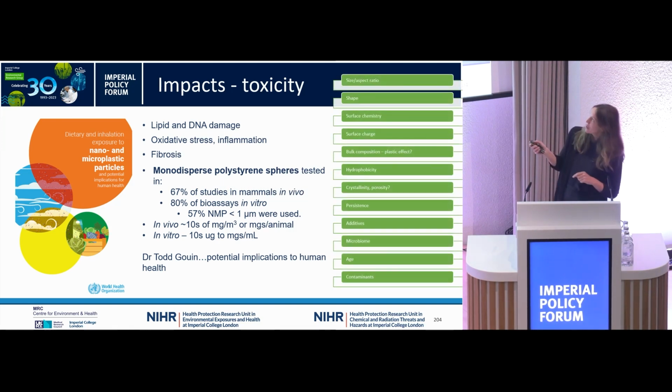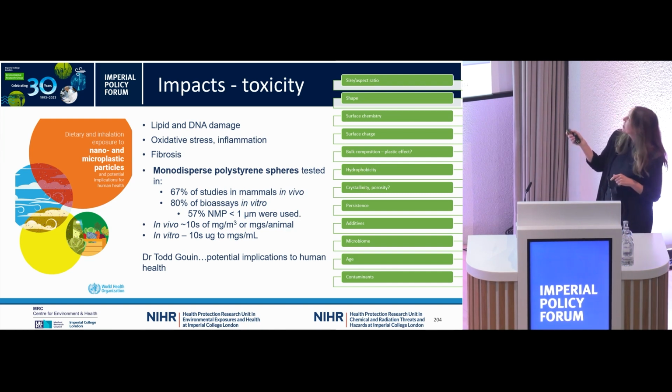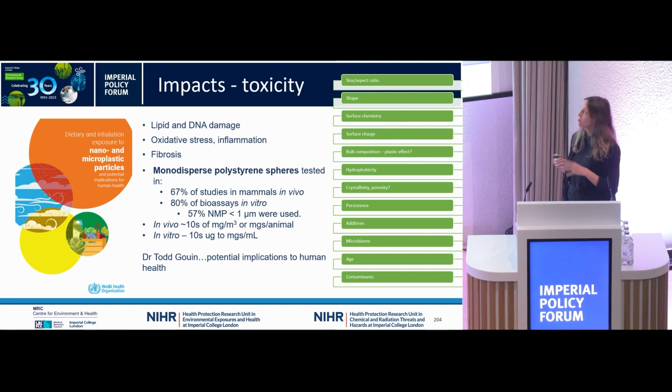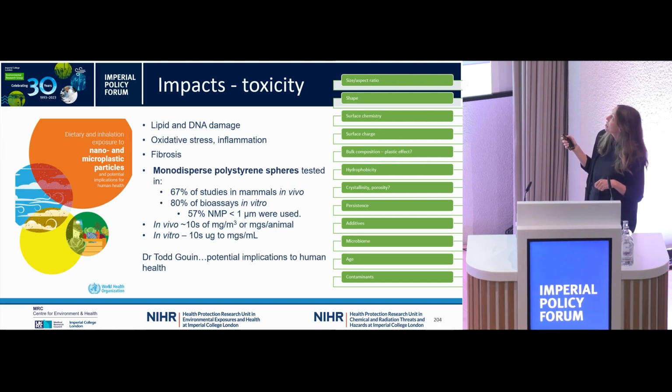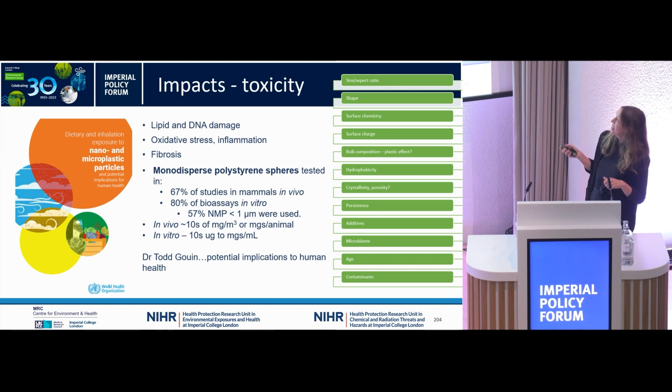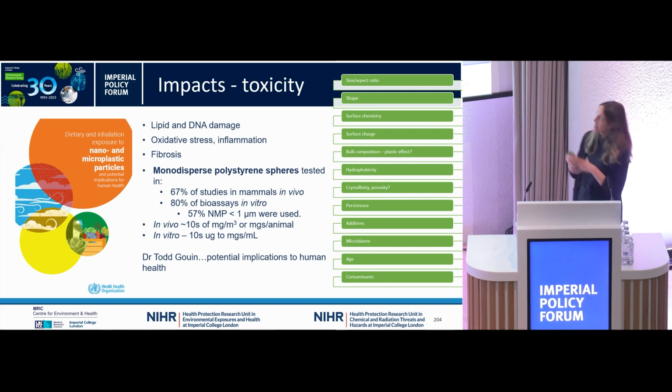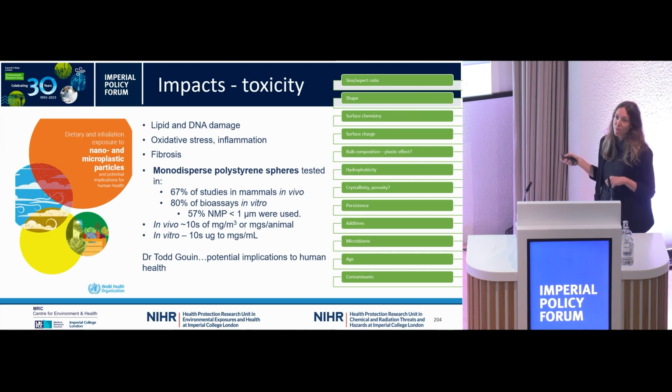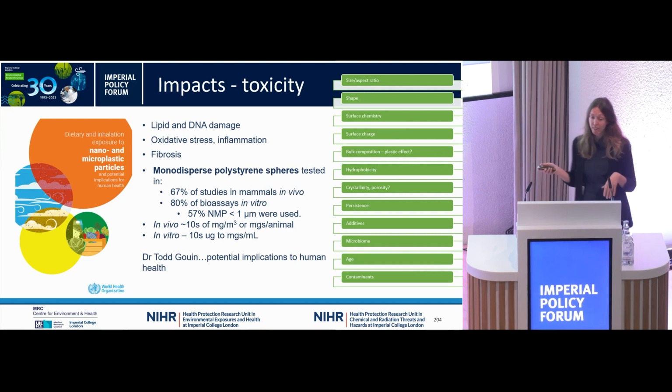So as mentioned, most of these studies use polystyrene beads, but if we look at all the different aspects of particles, you can see how we might overlook some of the issues with environmental microplastic. So we know shape, size, surface chemistry, surface charge. These are all important in particle toxicology, and they're not really covered in the tests that we've done so far, but equally we don't know much about the environmental microplastics in respect to some of these metrics. And so we really need to start thinking about more complex materials. And in addition, there's this extra layer then of environmental microplastics being weathered, having a microbiome on their surface, having additives inside, and then potentially having accumulated these contaminants from the external environment.